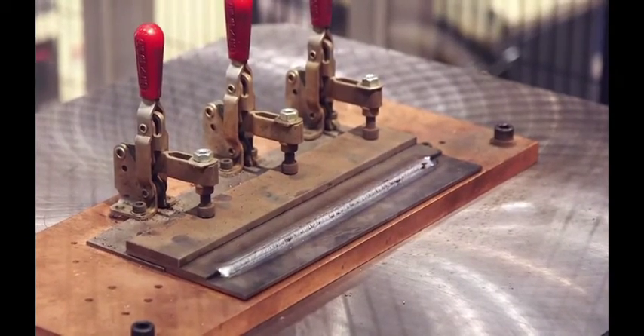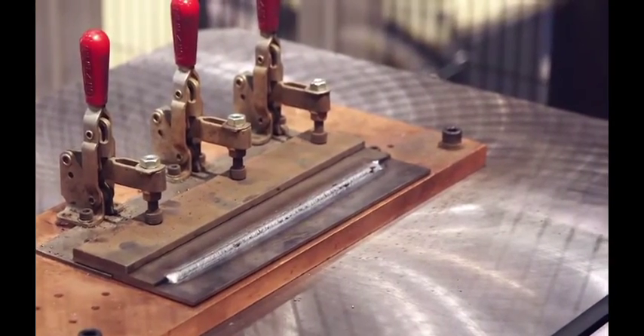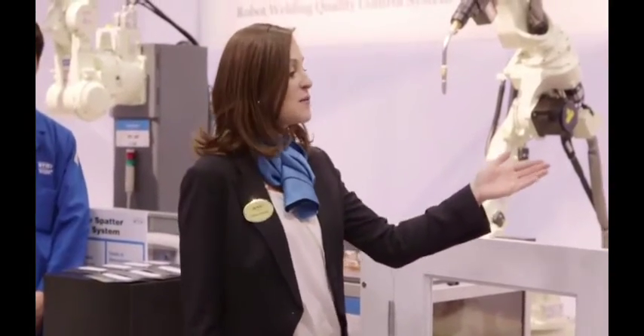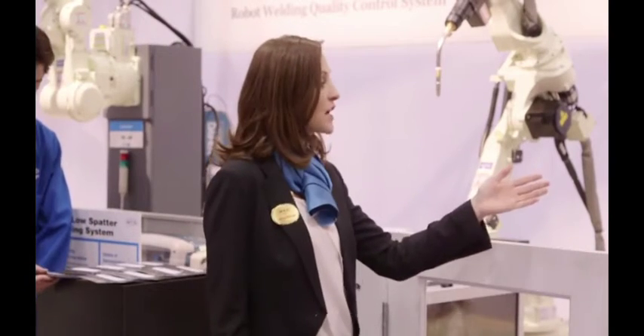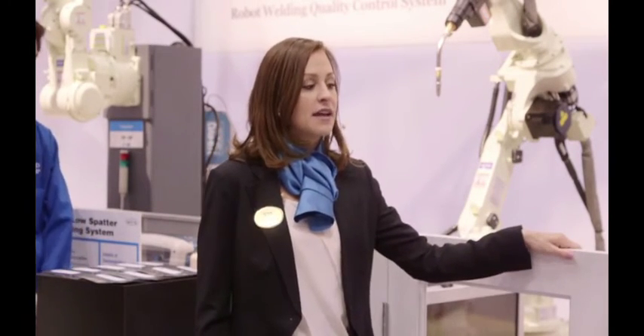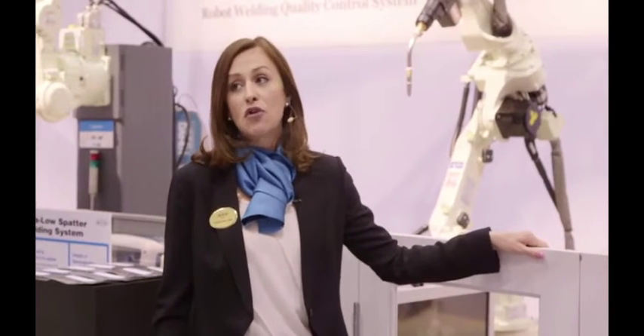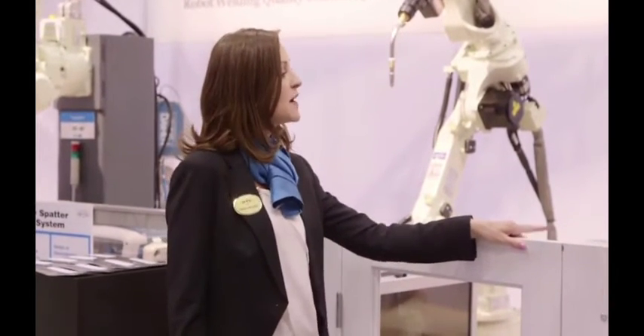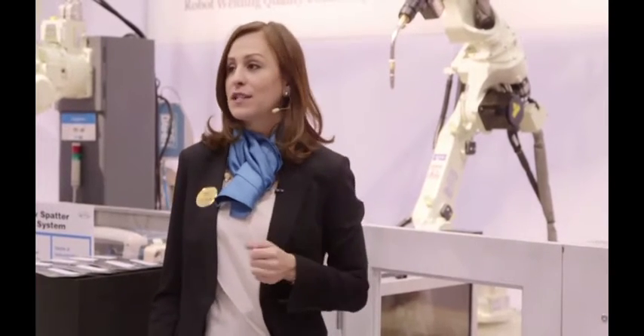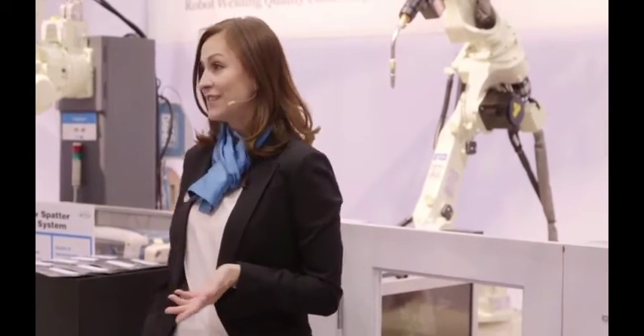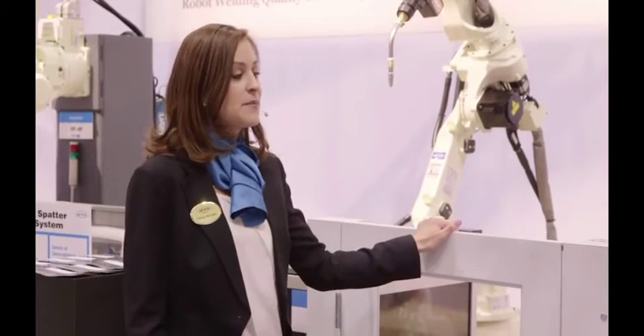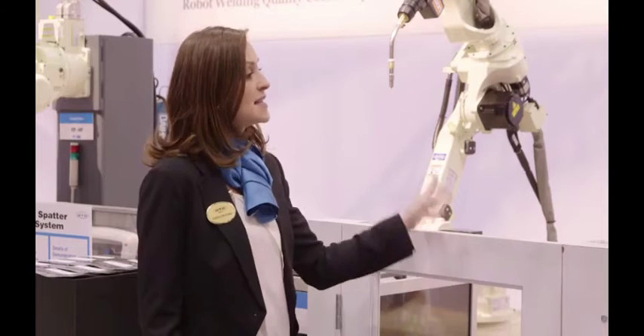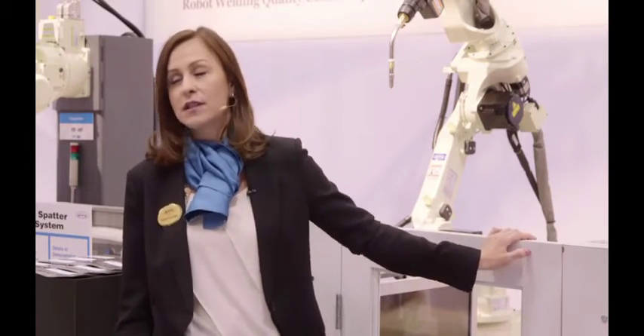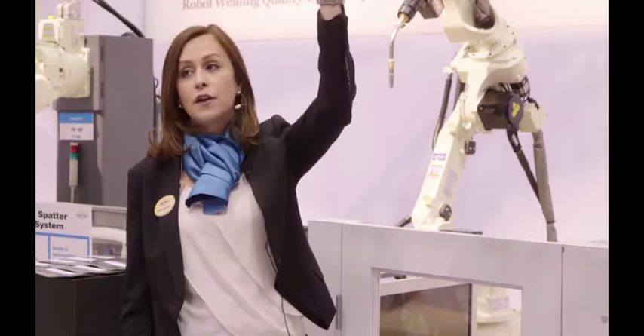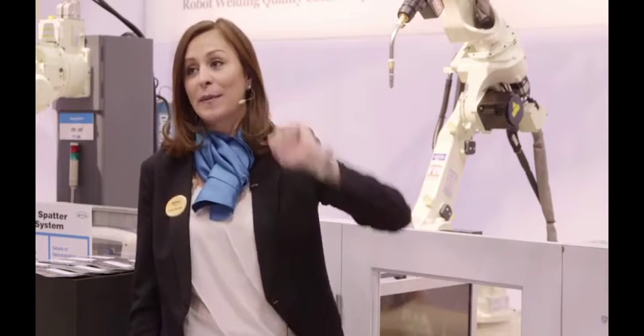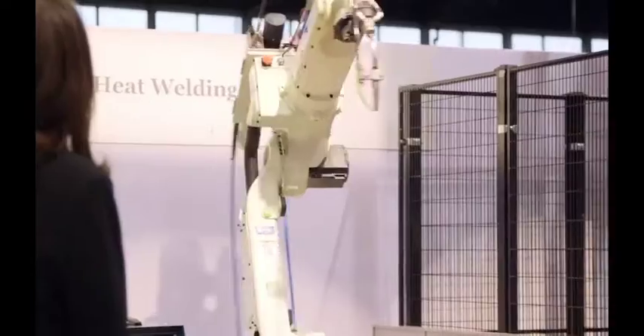Now let's move on. This section demonstrates cold tandem GMA welding with extremely low heat input compared to conventional welding. The arc is generated by the lead wire with the non-conducting cold wire inserted into the molten pool from behind. The molten pool is cooled down as a result, enabling welding with low heat input and less heat distortion. Next, in this demonstration, 3.2 millimeter mild steel is lap welded at 300 amps with a travel speed of 42 inches per minute and filler wire speed of 120 inches per minute. If you would, please.